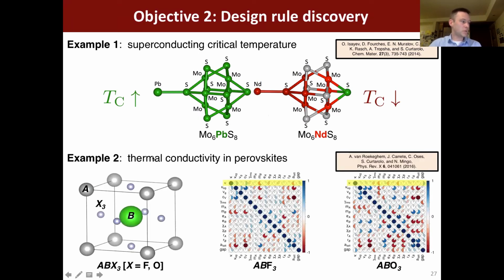Here's another example, which is on thermal conductivity and perovskites. So this is published in this paper here if you want to look it up for more details. On the left, what we see is that for fluoride perovskites, the thermal conductivity tends to depend on the atom that's on the B site, whereas for oxide perovskites, it tends to depend on the atom that's on the A site.